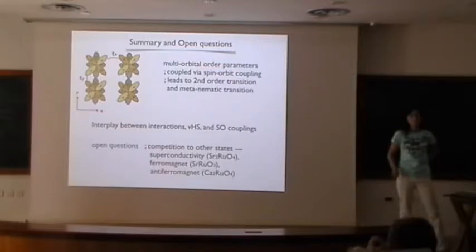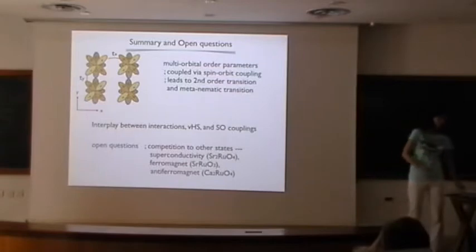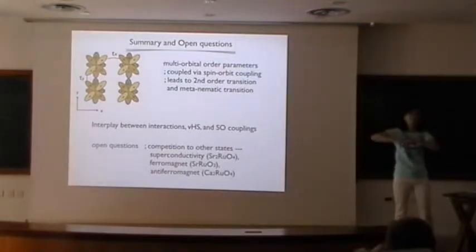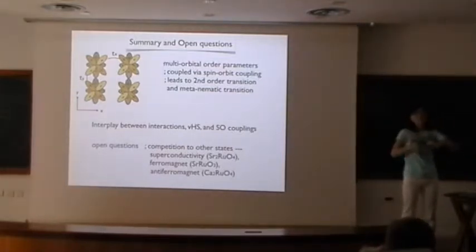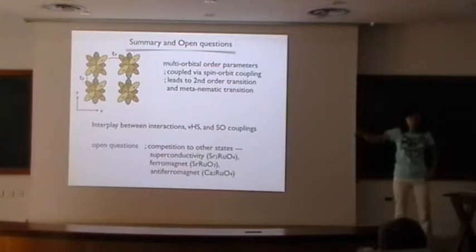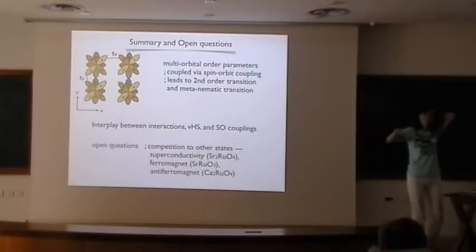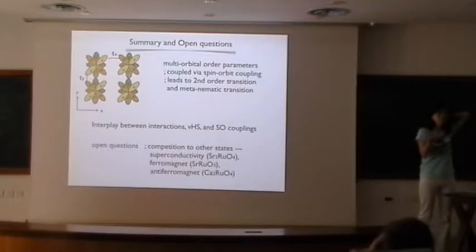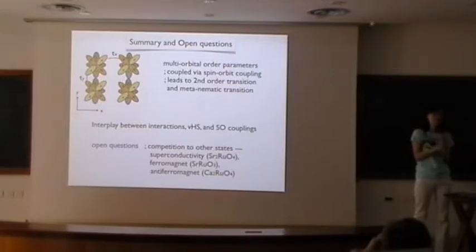C-axis hopping actually depends on the momentum, as you know well, because xz, yz, without having a tilting of the plane, you can actually mix with xz in the right up. You have to mix it diagonally. And that will give you some hopping, which comes as a sine kz sine kx, which will mix the xz and xy orbital. Yes, so it does mix it, but at a certain momentum, which appears at pi by 2, and pi by 2 is the maximum. So it does have a weaker effect, definitely. We have done it, in fact.